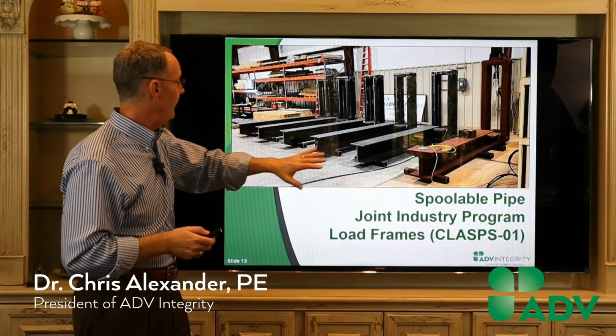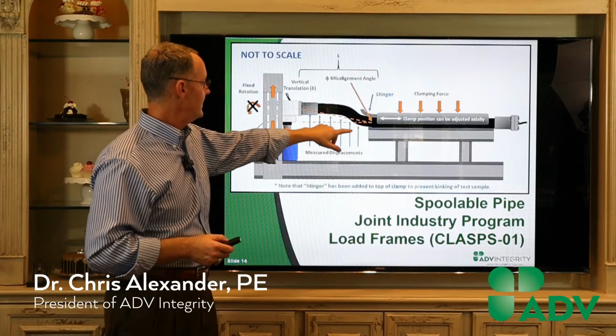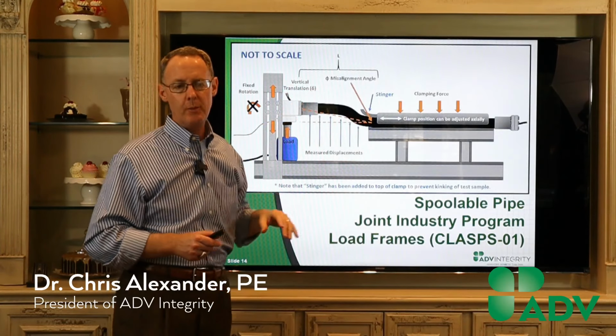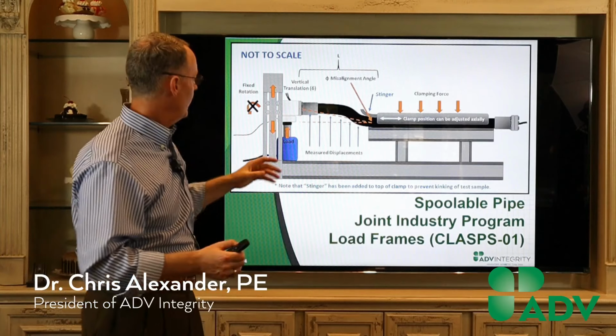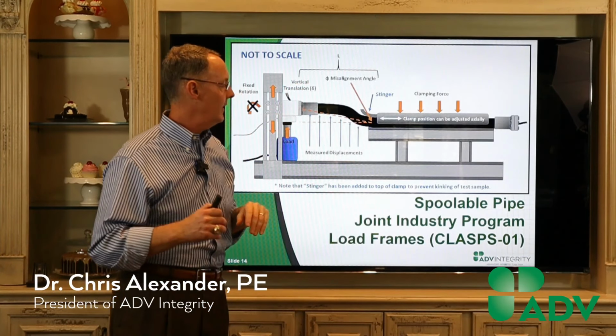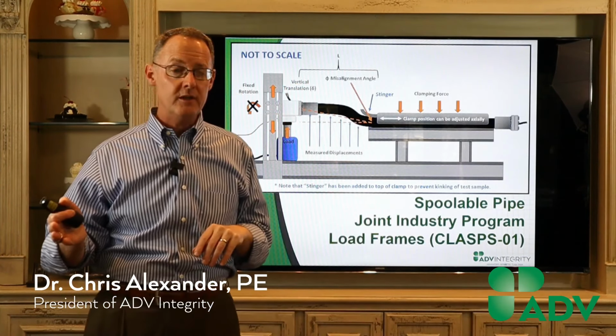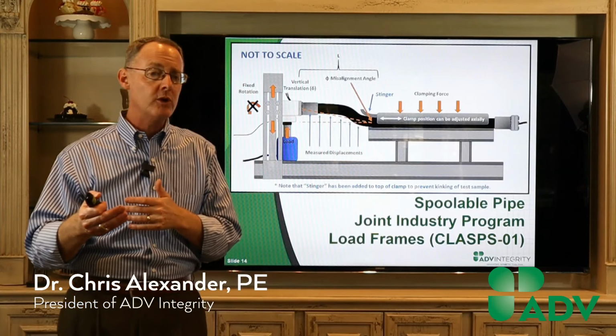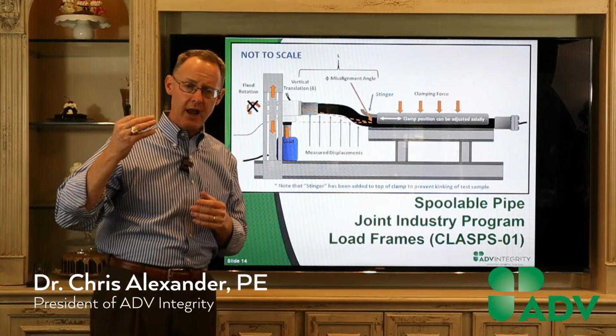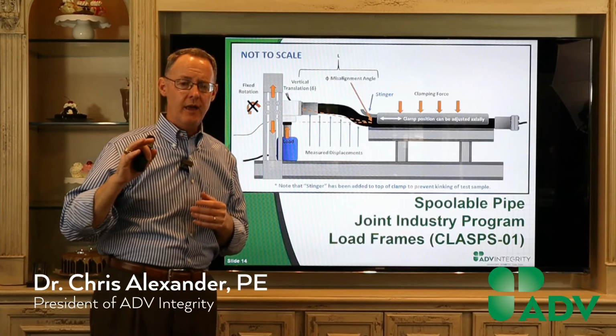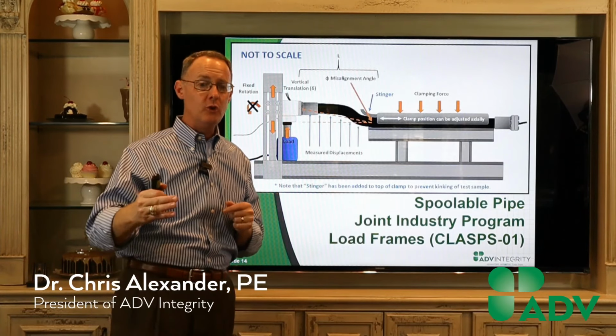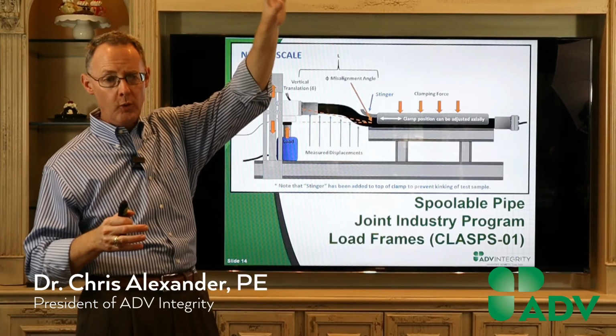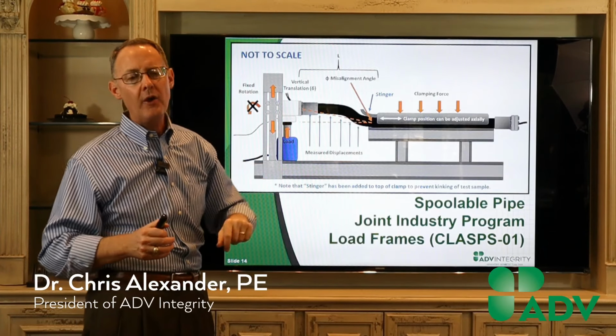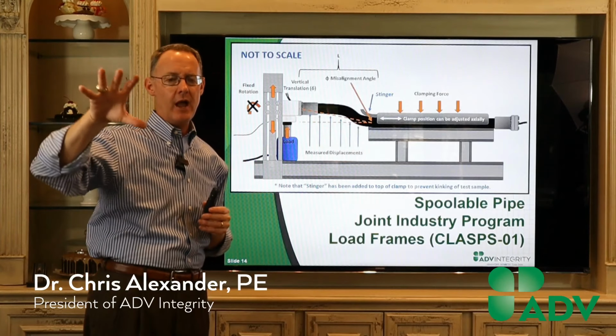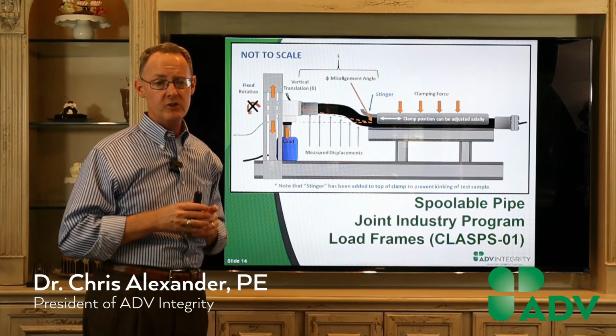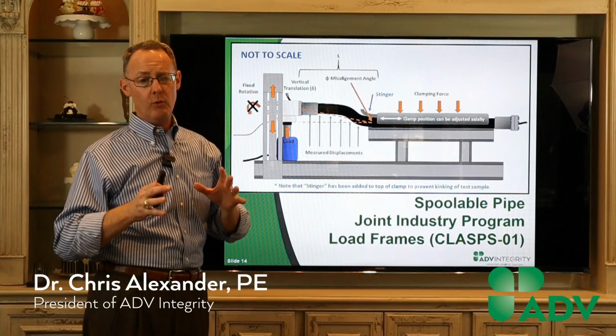So what we're doing, we built these rigs, and we displace the pipe, and the purpose of this JIP is we're looking at the connection. And so we displace the pipe, we hold it in place, hold it under pressure at 1500 PSI, which is the design pressure for these spoolables, 4-inch diameter, hold it for 1,000 hours. Everything looks good at that point. Then we induce 100,000 pressure cycles all the way up to 1,500 back down to around 100 PSI, and we just sit there and cycle. And then if they survive and we've finished a round, then we do a burst test in this position.